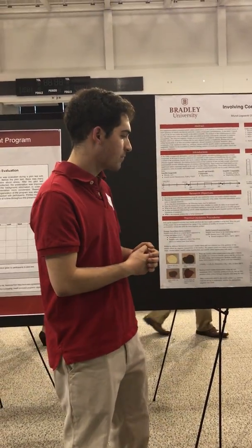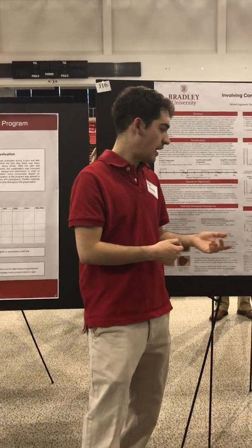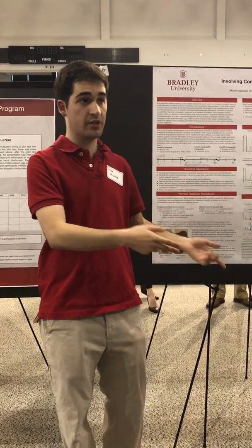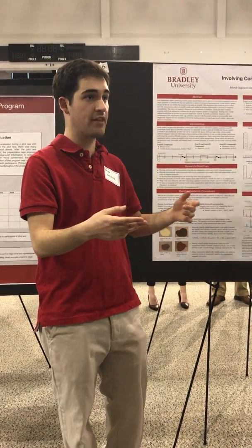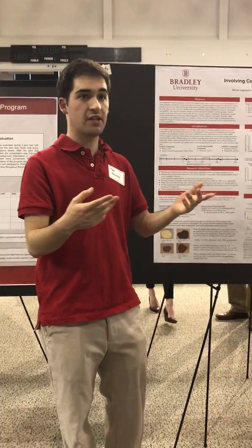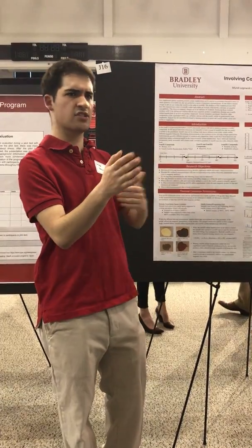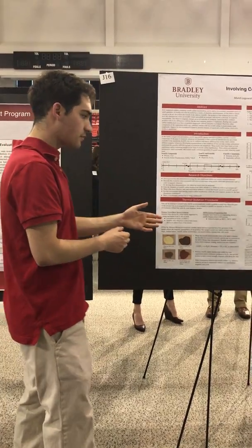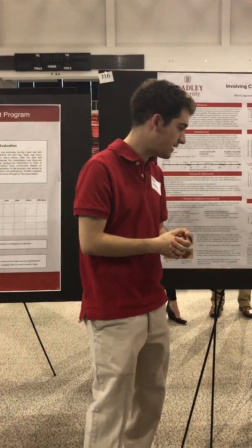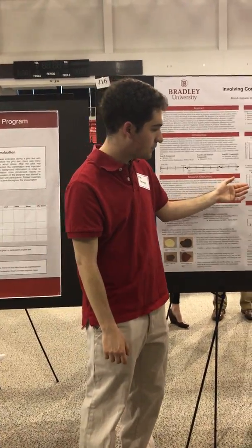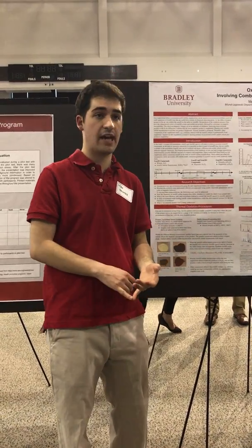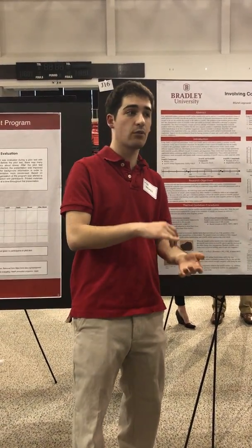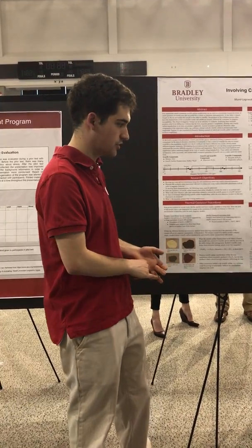And so we found this paper, and actually it didn't just occur to me to do that at first. I tried several different methods, and then my professor and I just went, oh wait, let's just do this, and it worked. And so we confirmed that it was maghemite, and here we just have 2 different runs, one of a supplement tablet at 700 degrees, and one of iron 2 sulfate and starch at 700 degrees.